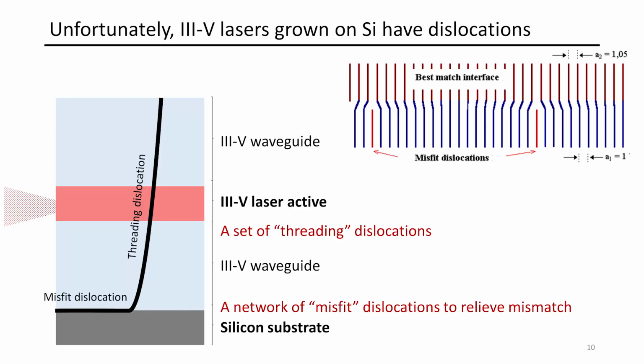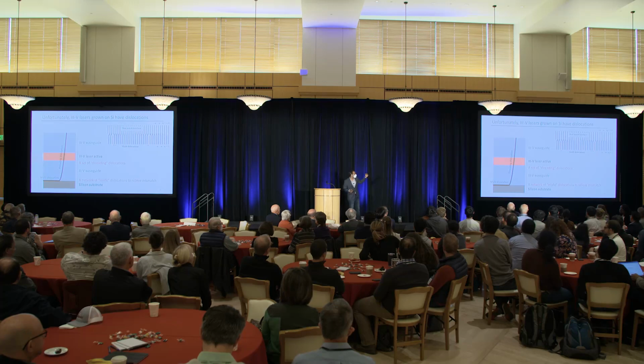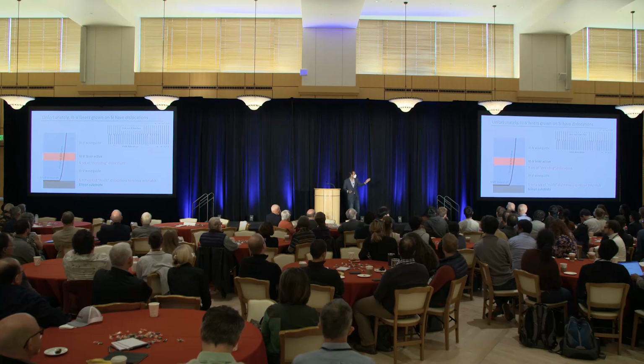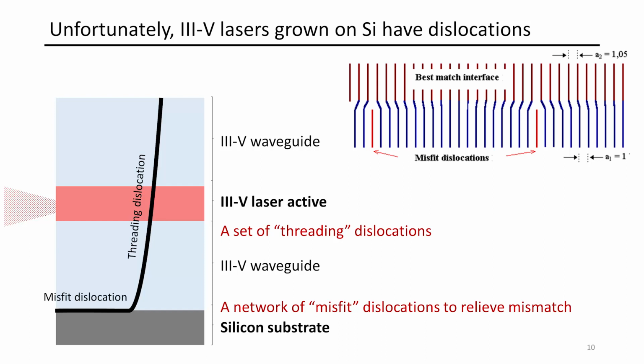So this is an example of a typical device. This is a III-V laser. It's a compound semiconductor laser that's grown directly on silicon, so some things will never change. You will have a dislocation at that interface. That dislocation is there because it is trying to mediate that mismatch between the III-Vs being differently sized than the silicon. So that dislocation at the bottom, we call those misfit dislocations. Very apt name, yeah? Misfit dislocations at the bottom.